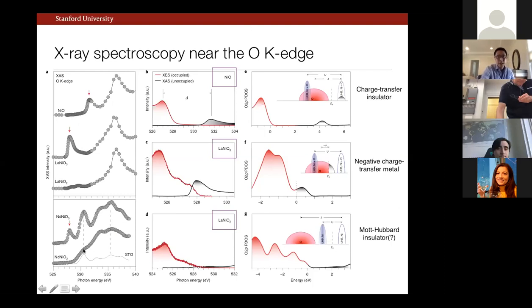And so similarly, you could go through the spectroscopy of looking at the occupied and unoccupied states to orient yourself in the world. So again, nickel oxide, the perovskite nickelate, and the infinite layer nickelate. And the bottom line summary, let me just stick to these cartoons here, is that we have a rather unusual regime that, despite being very much on the right-hand side of the periodic table, we believe is to some degree rather akin to the Mott-Hubbard insulating structure rather than a deep charge transfer insulator as found in the cuprates. Okay.